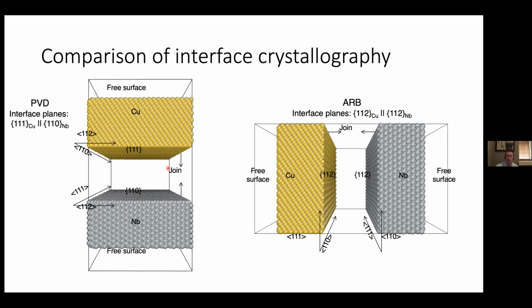physical vapor deposited layers. However, in the accumulated roll bonded layers, you get the same relative orientation of the copper and the niobium crystals. However, the plane orientation, so the Miller indices of the facet planes that join on the interface, are different: 112 in copper and 112 in niobium. So different from what they are in the PVD case, right? So the ARB interface planes are different than the PVD interface planes. And it turns out that this has an enormous influence on the properties of these interfaces.